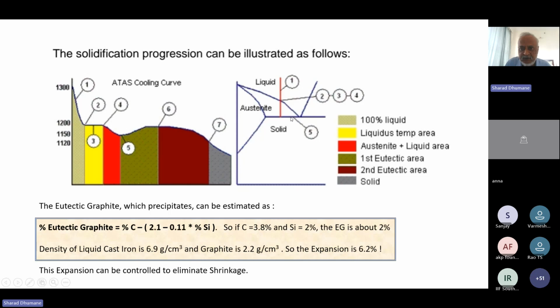Then at point 5 here, there is a slight increase in temperature as well. All that liquid suddenly solidifies, and that particular phase reaction contributes to a slight increase in temperature. So this is point 5, and then point 6 is below. So as it moves from this to this over time, temperature slightly increases, and then at point 6 it starts plateauing down, it becomes constant, and then it starts decreasing. So this is what happens when a particular casting of a given composition is solidifying.